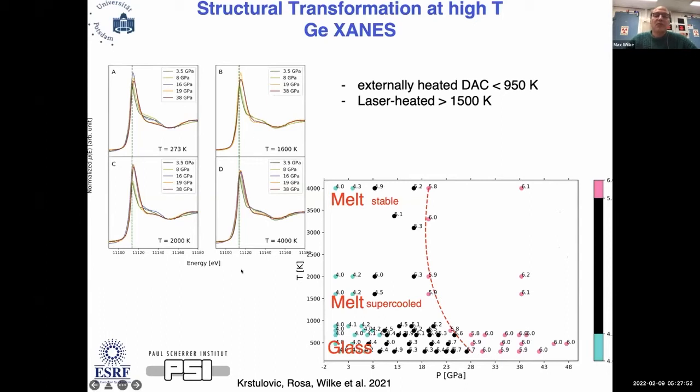Maria, with his calibration, basically looked at all the spectra that we measured and mapped out the coordination number, given here either in color code or as the numbers. We see a region where we're really in the glass below 1000 Kelvin. This is all glass, and we can see that there's only a very slight difference between room temperature and higher temperatures.